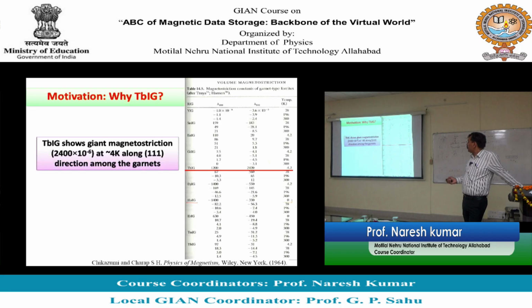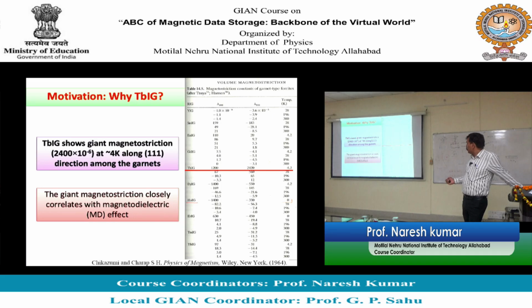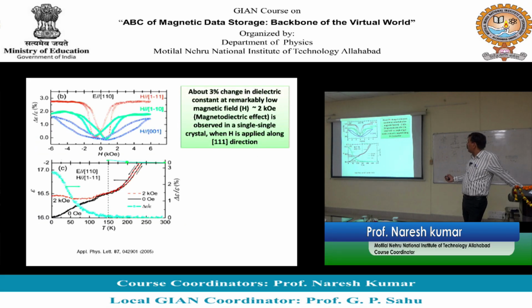So why did I choose terbium iron garnet? If you look at this table, this TBIG gives you maximum magnetostriction when you apply a magnetic field along one-one-one direction. What is magnetostriction? When you apply a magnetic field, it changes its dimension. So this can be used for magnetoelectric applications. This shows maximum magnetostriction when the field is applied along one-one-one direction. The issue is, in single crystal, it has shown about 3% change in dielectric constant by changing the dimension.